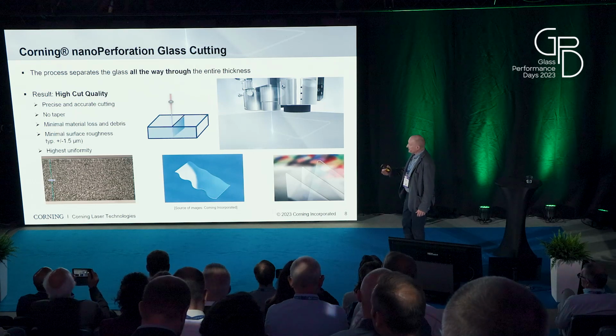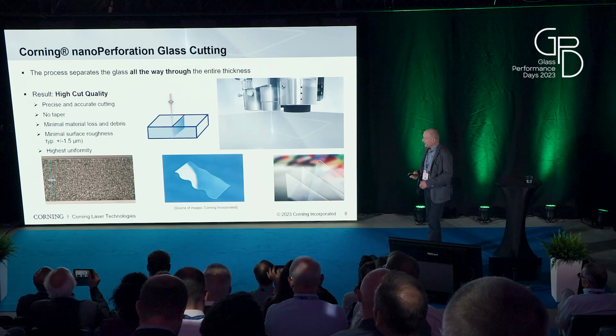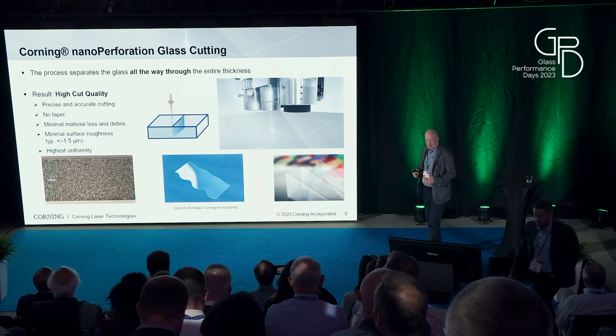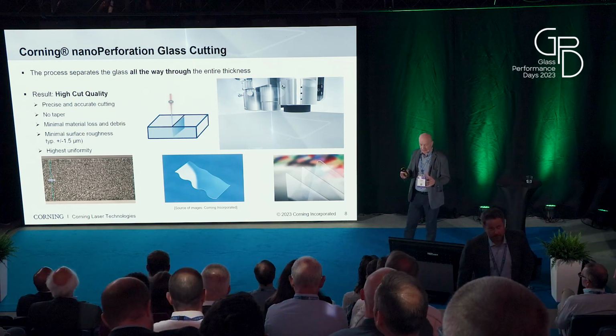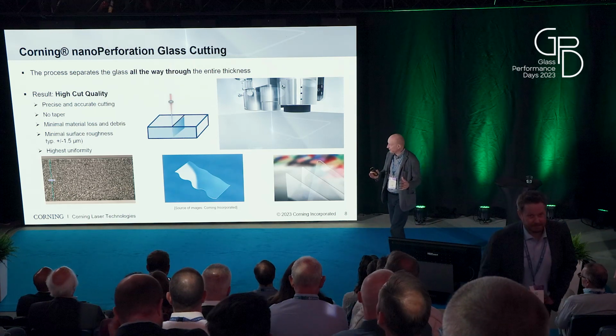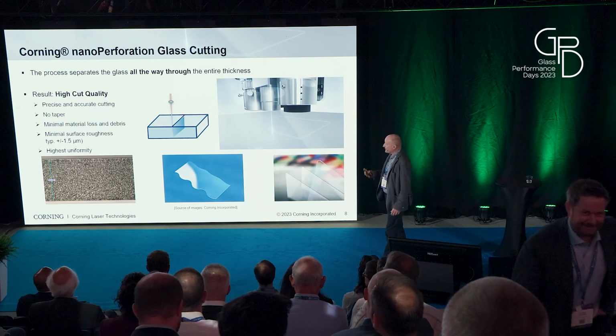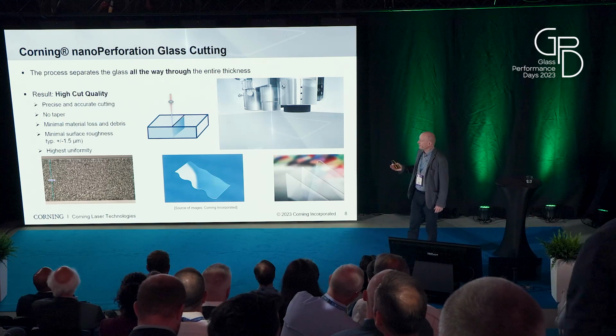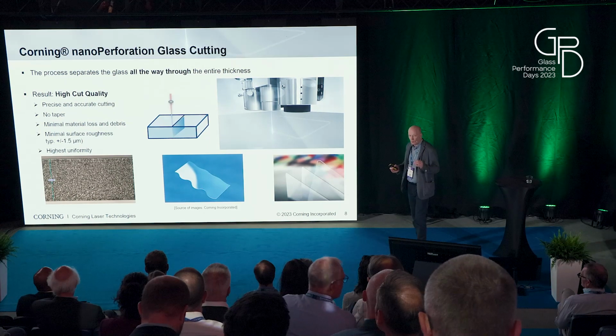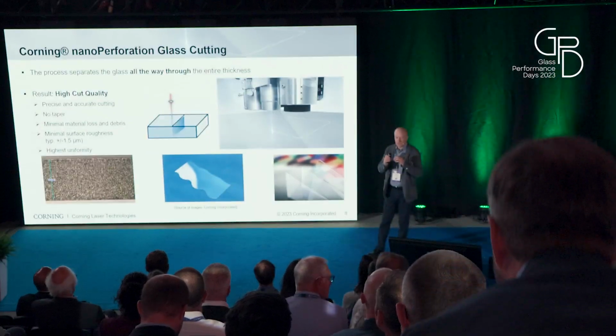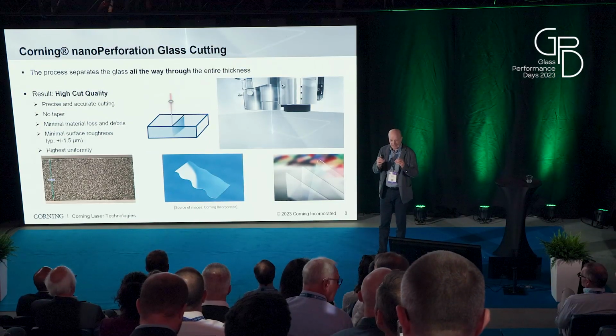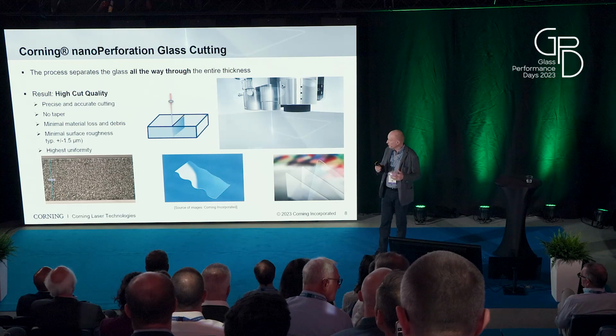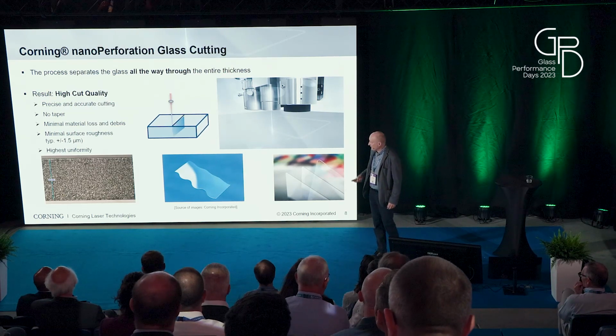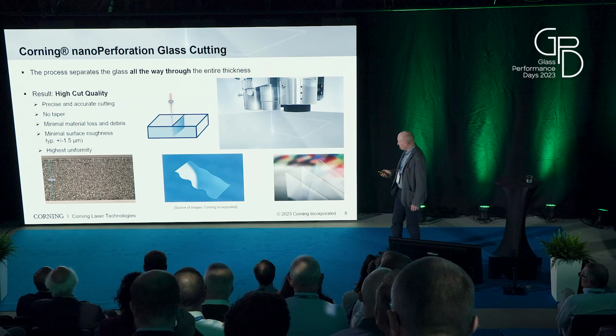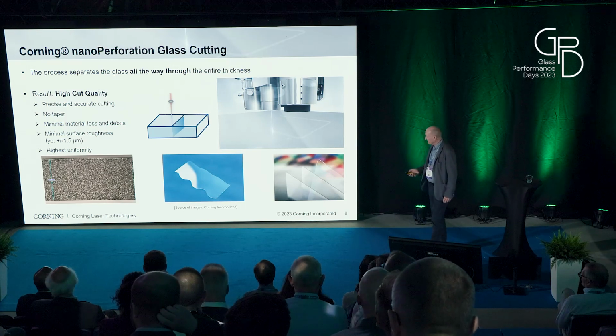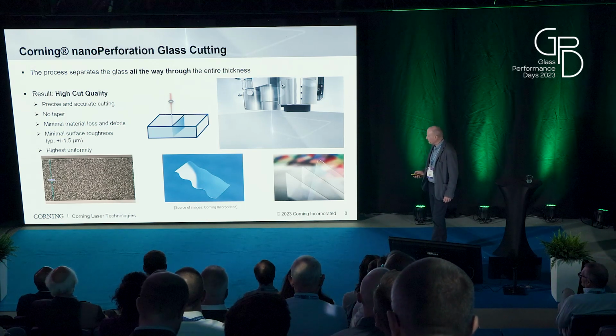The result is very high quality cuts. It is very precise and accurate cutting. That's why we can also do cutting of freeforms and essentially net shape cutting, as you will see later. There is no taper and practically no material loss. The only little debris comes from a bit of chipping, but otherwise there is no material removal. The surface roughness is very low, and we have very high uniformity. These are just some examples to illustrate what we can do.